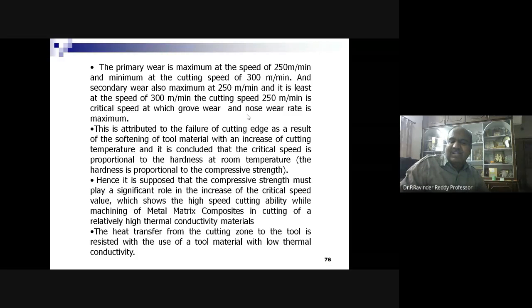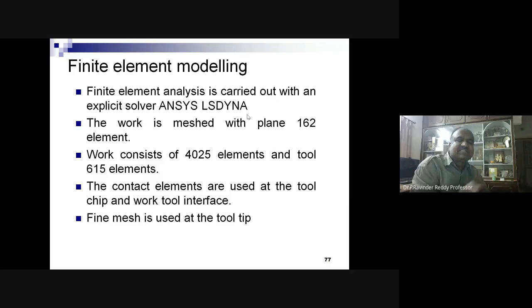The heat transfer from the cutting zone to the tool is resisted with the use of tool material with low thermal conductivity. For the same tool wear, we wanted to model, simulate, and find out the wear rate. So the fundamental modeling which we have done for the same, using ANSYS LS-DYNA, we performed the analysis. The work is meshed with the PLANE 162 element. Work consists of 4025 elements and tool 615 elements. The contact elements are used at the tool-chip and work-tool interface. Fine mesh is used at the tool tip.